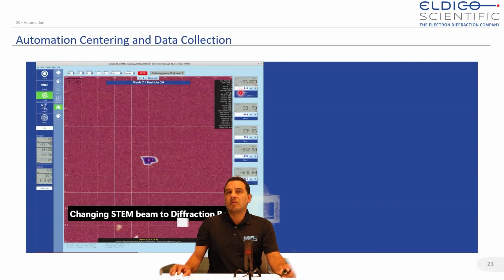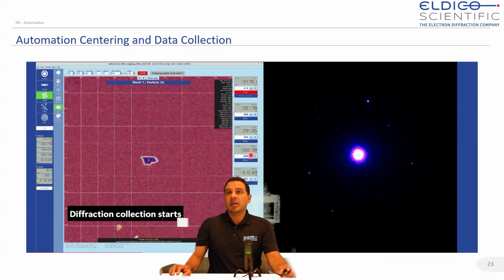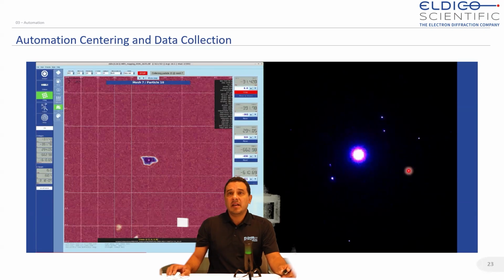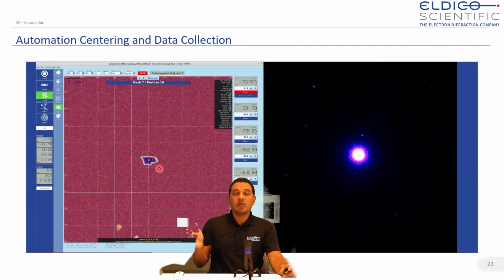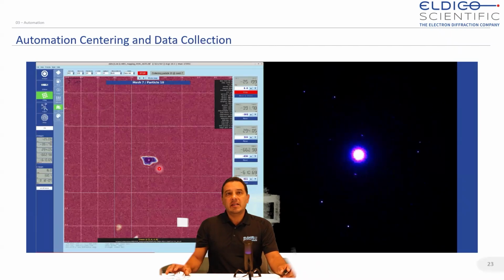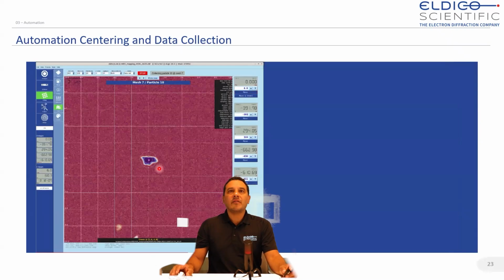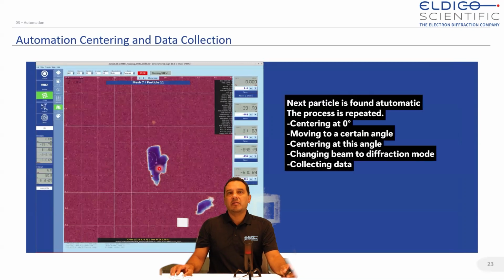So now you see here the crystal has been aligned. And now if we go on this small range on automation, then we can get diffraction on this particle from the range that we have given, as you can see here on the right-hand side. Now the process is very simple. Once you have collected your diffraction data, the software would move automatically to the next particle. That means we are moving our motors, we are not moving our beam. The particle is put again in this position. A STEM image is taken at 0 degrees to center in the beam, in the focus part of the beam. It's moved again back to the angle where we want to start our diffraction, recenter again, and then the continuous rotation starts. So now you see it here in this particle.